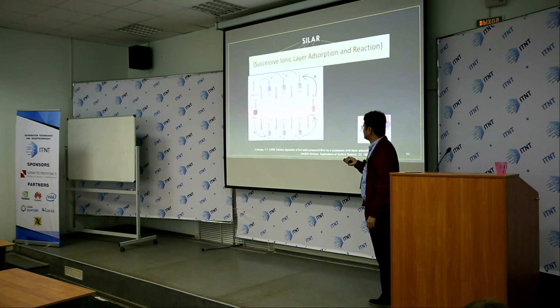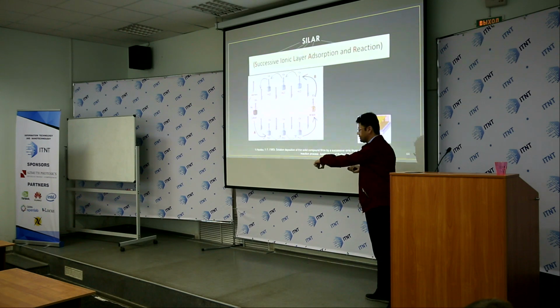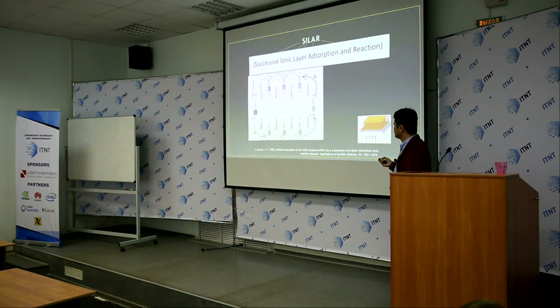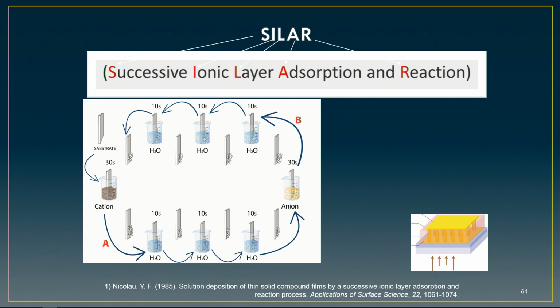For example, for 30 seconds we immerse the polymer in the cation solution, then rinse 3 times, each for 10 seconds, and then in the anion solution, for example, cadmium ions react with sulfur ions here to prepare cadmium sulfide nanoparticles. This is the first cycle. From here to here, we have the first cycle. If we continue this process, the second cycle, the third cycle, the fourth cycle, this is the growth mechanism of semiconductor nanostructures inside the polymeric matrix.